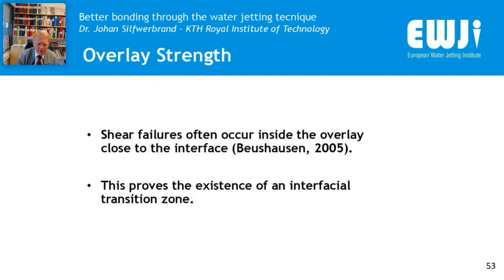And then overlay strength. Shear failures often occur inside the overlay, close to the interface, according to Beushausen, a South African researcher in this area. And this proves the existence of an interfacial transition zone. So that means that you shouldn't use too poor concrete for your overlay. You should have at least moderate quality. I wouldn't go less than 40 megapascal in concrete strength.